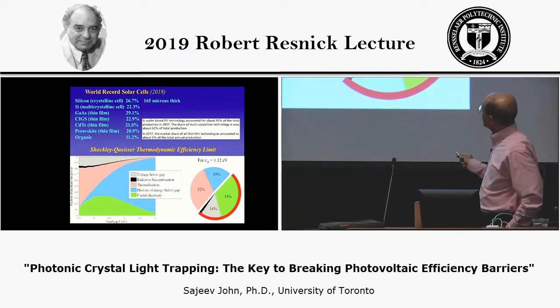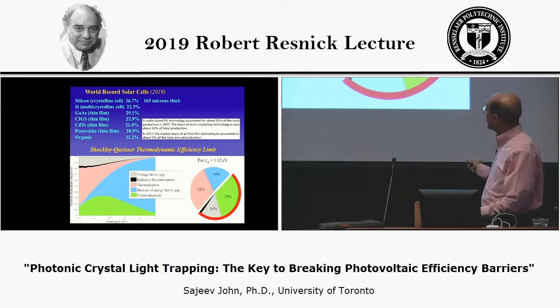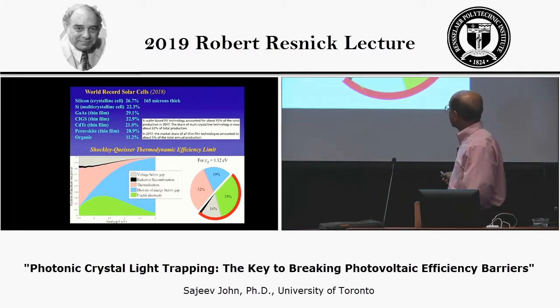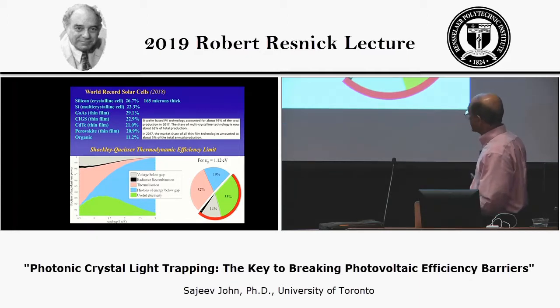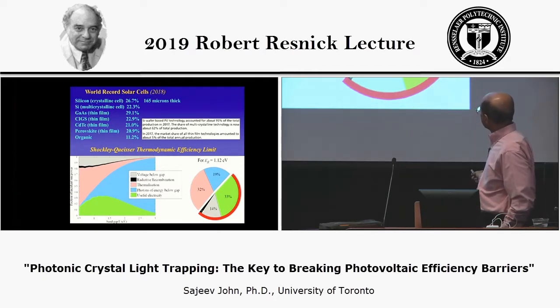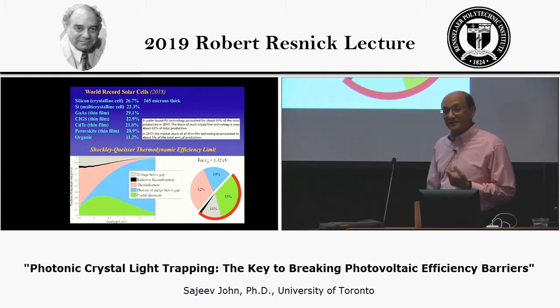There's about a third that goes away into thermalization. 19% falls below the band gap and cannot be absorbed. And then there's also some entropic effect due to finite temperature, which reduces the voltage of the solar cell. So about 14% is lost there. But they suggested that the maximum thermodynamic efficiency at room temperature for a silicon solar cell would be slightly under 33%.